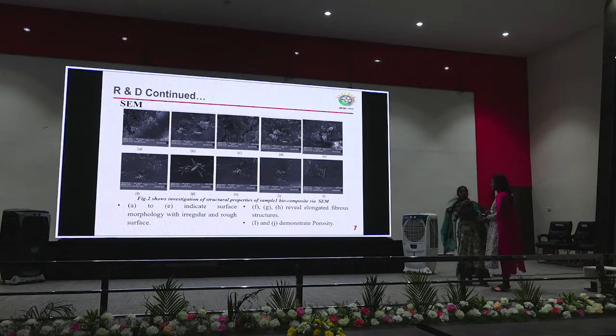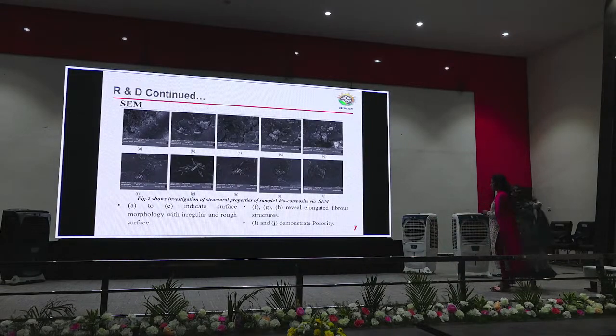SEM is used to characterize the surface morphology. Figures A to E indicate a surface morphology that is irregular, porous, and rough, which indicates acoustic property and sound damping. Figures E, F, G, H show an elongated fibrous structure which is suitable for sound dispersion, and I and J demonstrate the porosity which helps the sound absorption property. Next.